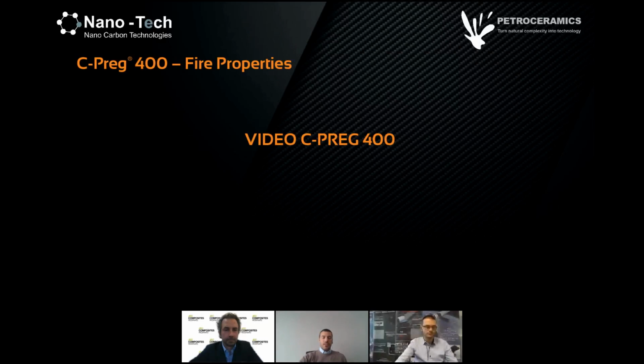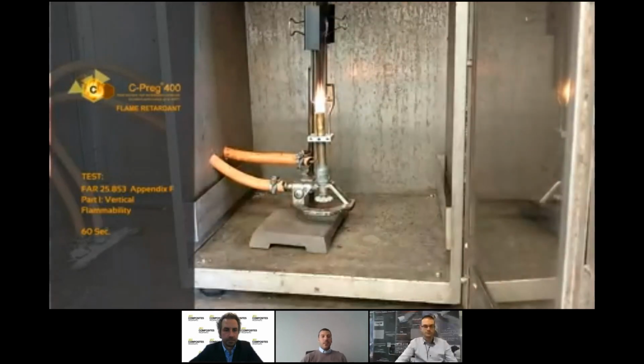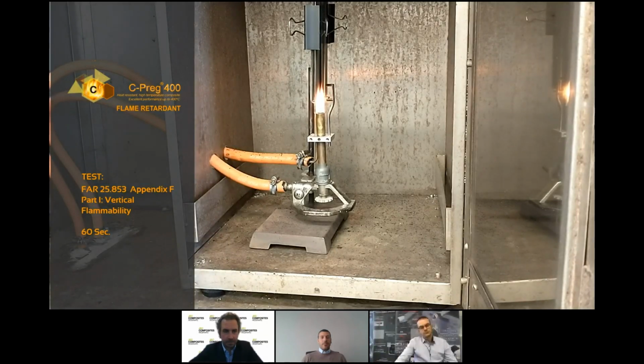Here we will show a little video of the FAR test vertical flammability. Thanks, Benjamin. The video lasts a bit more than 1 minute. We keep it, so you will see the test. As you can see, there is no ignition, so the material is not burning, and will not burn for all the minutes of the test, as you will see. It's already about 50 seconds of testing. No ignition at all.